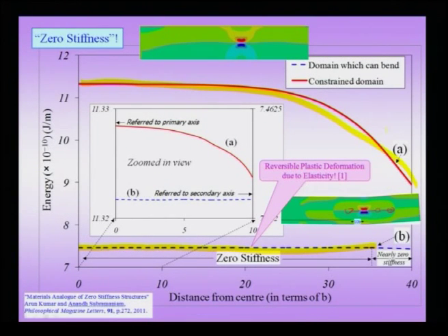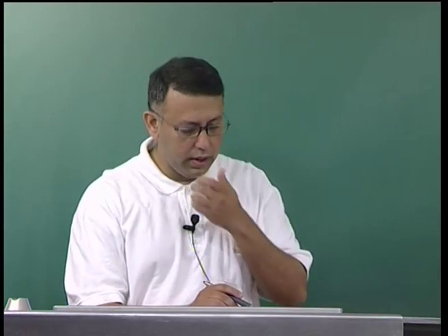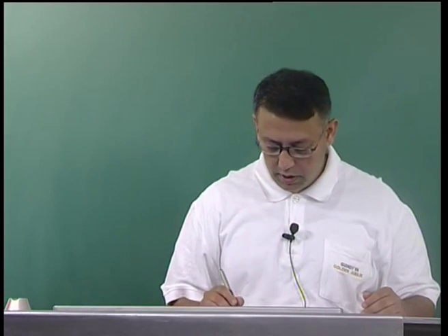In such a thin plate, not only does the dislocation bend the domain, and not only is there a slight relaxation with respect to the energy in a bulk crystal because of this bending, in addition to the fact that the amount of material strain is small, but more interestingly, the dislocation now resides in a state of neutral equilibrium with respect to its configurations. This has been termed neutral equilibrium material structures, and these are very special structures which were discovered very recently.